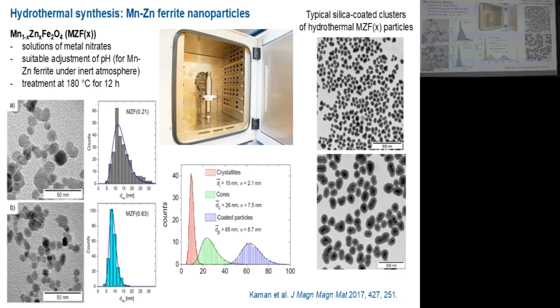There is quite broad size distribution, but still reasonable compared to other methods, as we will see later. And such particles prepared by hydrothermal method typically form clusters. Even if you apply some stabilization, like with ammonium citrate, they will form some clusters. So upon coating with silica or some polymer, you will typically observe such small clusters of individual crystallites coated as a whole with your material, either with silica or polymer.